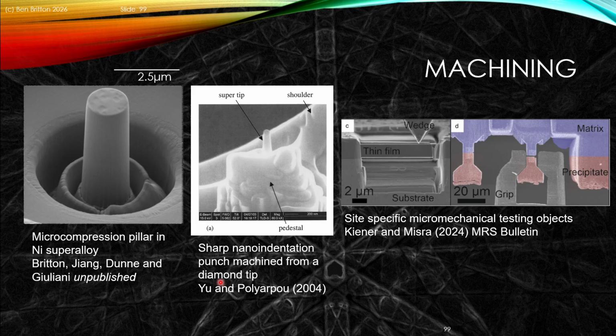So here are some examples. In this example, we could, for instance, make a micromechanical test specimen. So this is a micropillar. We've actually seen this as deformed in a previous lecture in this series. We can also sharpen an indenter tip, and so we can make a sharp nanoindenter by effectively cutting and leaving a very sharp pillar on a pedestal in there.